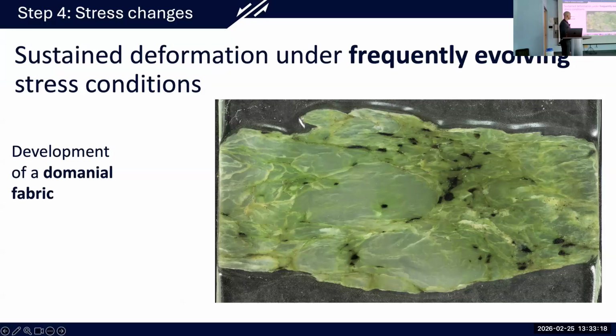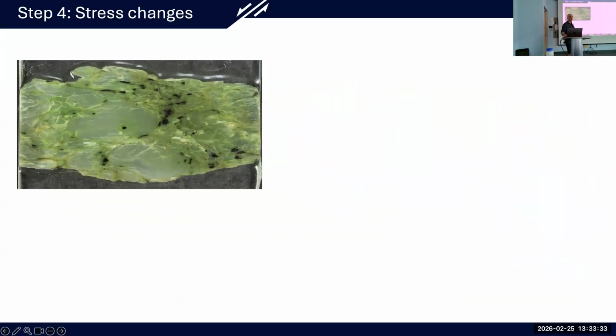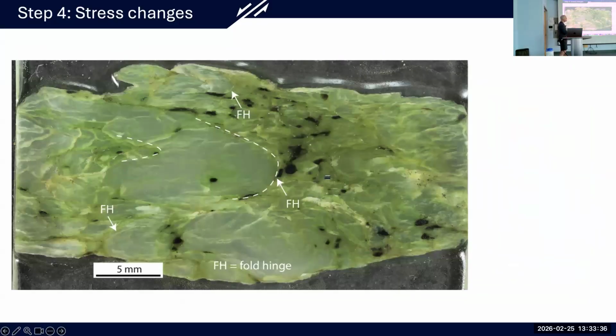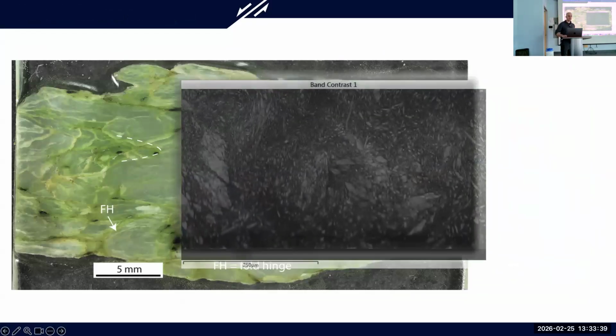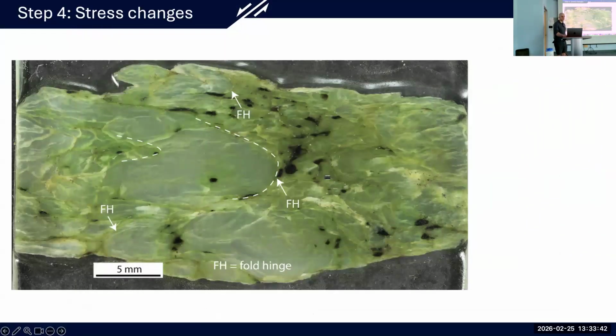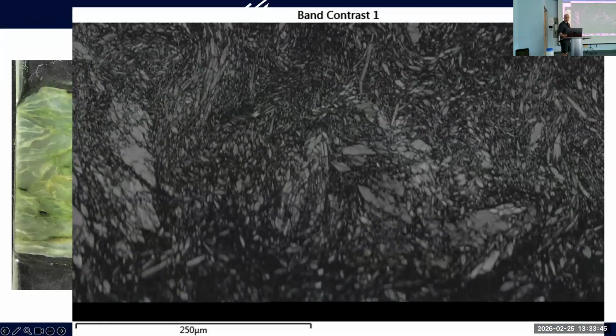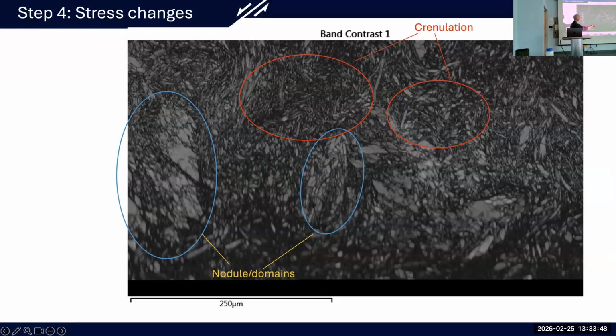And so all nephrite that we examine, all this high-grade nephrite jade, has what we call a domainal fabric. So if we examine the fabric of the nephrite, we can find elements of, for example, folds. Here we can see a hinge of a fold. If we look closely, we can also find hints of ancient crenulations that were preserved. These nodules and domains, these crenulations, all those previous fabrics, the schistose, the crenulated, the folded, have all been preserved